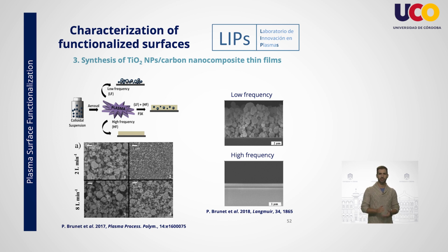This solution was then introduced using either a nebulizer or an atomizer into the chamber of a dielectric barrier discharge reactor with a well-controlled atmosphere. Scanning electron microscopy is a very useful tool to characterize the structures obtained for each case. According to the images in the lower left corner, it can be seen that by changing the nitrogen flow, clusters of nanoparticles with different appearance are obtained. Although their size is similar, the nanoparticles obtained under lower fluxes are more isolated.